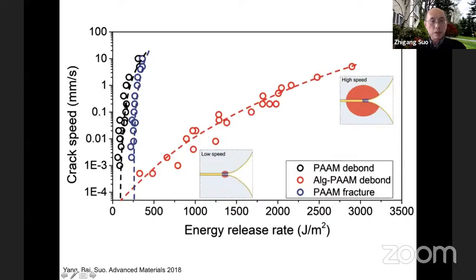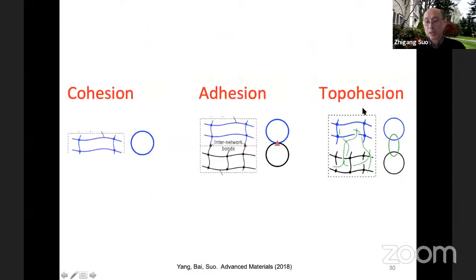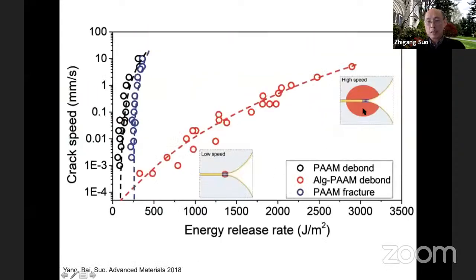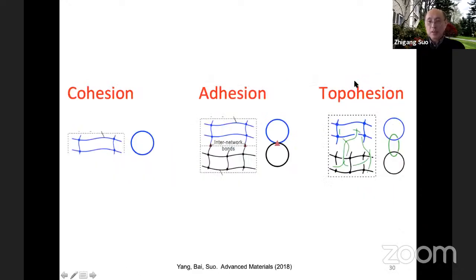So these two curves are the previous two curves. Now the scale is totally different. Remember, we have tough gel, right? So if we use alginate to bond two pieces of tough gel, then the toughness becomes enormous. Of course, we know that—you don't need to change the bond, you can use the same alginate bond. All you need is dissipation that can amplify your energy all the way to thousands. So that's what's happening. That's good.